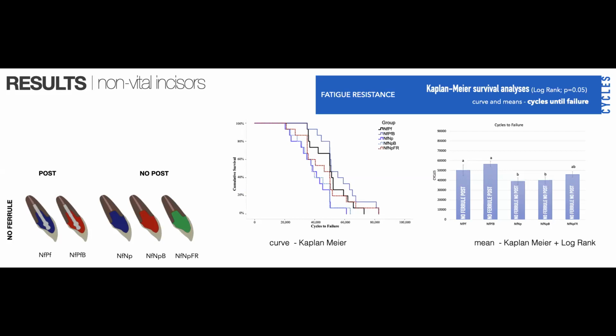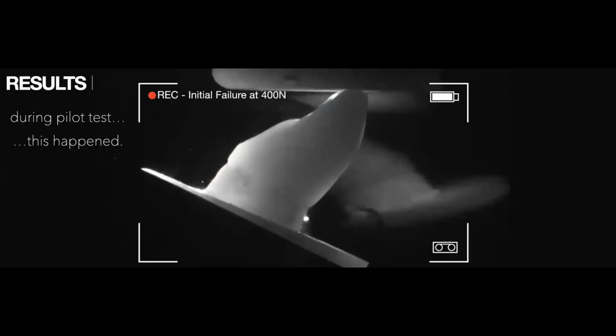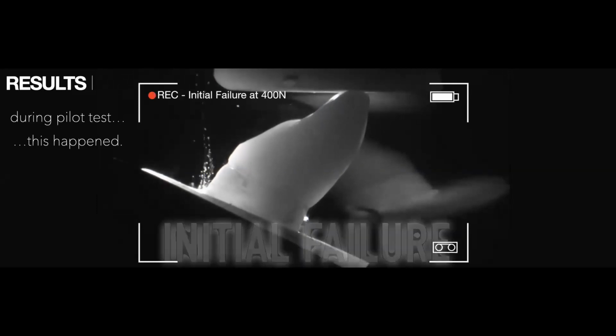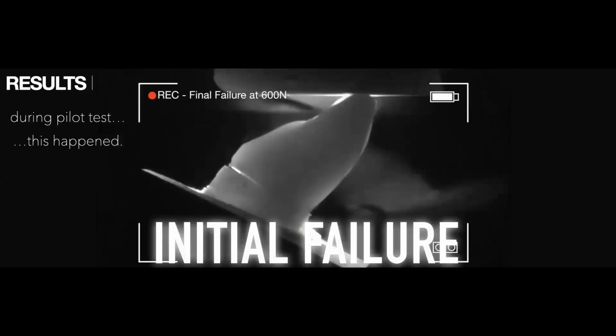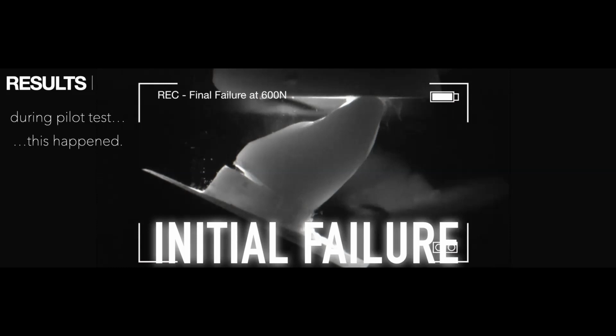But Priscilla showed us that those results are biased. Why? Because of what we saw during our pilot test. As you can see, that's what we saw during the pilot test. There was a failure. I could hear it, but for some reason the machine could not understand that as a failure. So we had to record everything and see when those failures happened, and calculate the amount of force and the cycle. When we did that, everything changed.